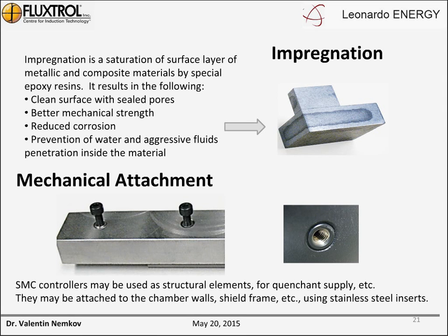The penetration for our materials, soft magnetic composite of Fluxtrol type, is about 5 millimeters. You can see that on the right side. I want to mention also that soft magnetic controllers may be used as a structural component, for example, inside of an induction coil for quenching supply, or they can be attached to the chamber wall, shield frame, and so on, using stainless steel inserts. It's the best well-proven technique.